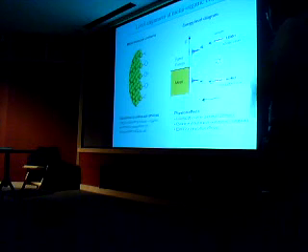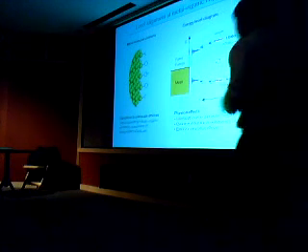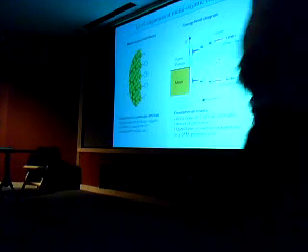And the change of the level depends on a number of physical effects: interfacial charge transfer, quantum mechanical coupling between the molecular state and the metallic state, and electron correlation effects. Now, density functional theory, in principle and also in practice, will probably give you the first two right, but whether it could give you the third one right is problematic. In fact, we find that the DFT levels are not adequate at all.